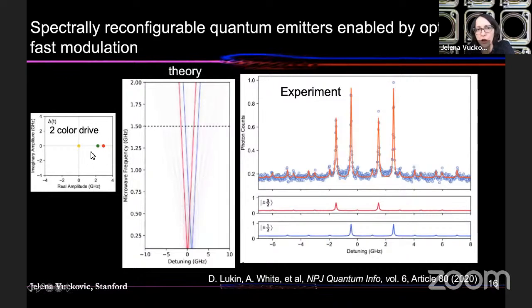So here is a 2-color drive. Here is a theoretically predicted behavior of the system, and we measured it at 1.5 gigahertz drive frequency. And here is the experiment. And you see 4 peaks at the output. Two of them correspond to the spin 3/2 manifold. The other 2 correspond to the spin 1/2 manifold.